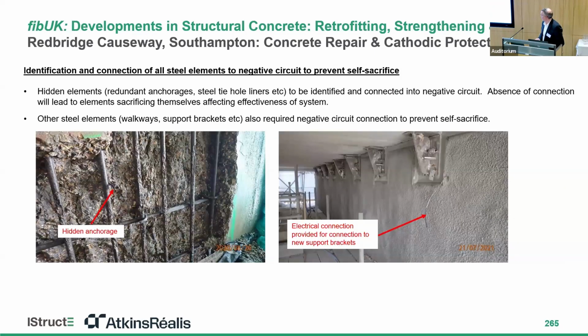This is showing a detail of a standard concrete repair. You can see the corroded reinforcement, and in the far right, you can see the bar that was clearly cathodic, which is in fine condition. And also, this is an issue that we found on site, the shutter anchors were pretty much largely discontinuous. So that was an element of work that wasn't included for initially. So all of those had to be found and made continuous with the reinforcement, otherwise they would have corroded. And if there's an overlay, it would have blown the overlay off.